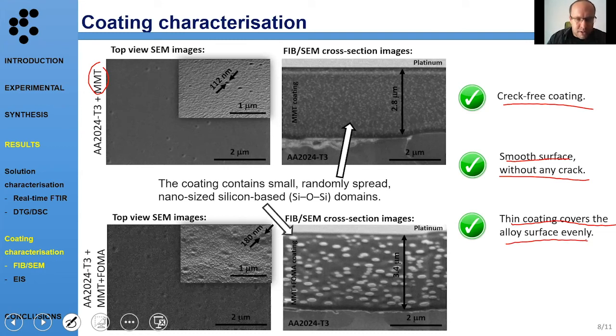This is very good. But on the other hand, we can see very small, nano-sized silicon-based domains which are randomly present in our coating. Moreover, we can see these domains also if we take a look at the cross section of this coating. We can see that these silicon domains are present also inside of this coating. However, if we take a look at the thickness of this coating deposited on aluminum alloy, it is around 2.8